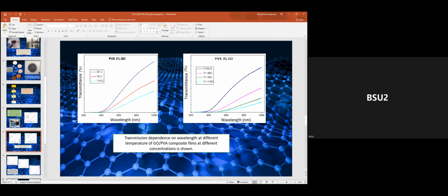Transmission dependence of wavelength at different temperature of graphene oxide polyvinyl alcohol composite films at different concentration is shown here. The maximum transmittance was observed for graphene oxide polyvinyl alcohol with 2% and 3% concentration film and dried at room temperature.